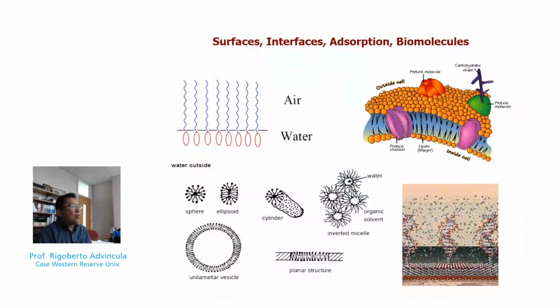Now, interestingly, surfaces and interfacial chemistry is also biological. In fact, at the air-water interface, which is one of the basic methods for investigating surfactant properties, one can look at the anisotropy of this phase, such that you can have selective orientation. Or one can look at micellar phenomena, formation of vesicles or higher ordered micelles in interfacial chemistry, and its importance in short and long range ordering.